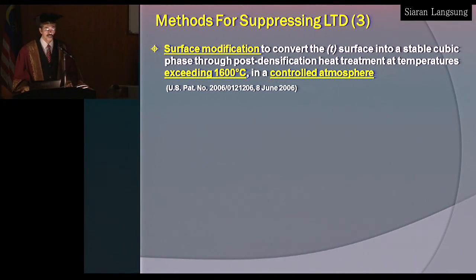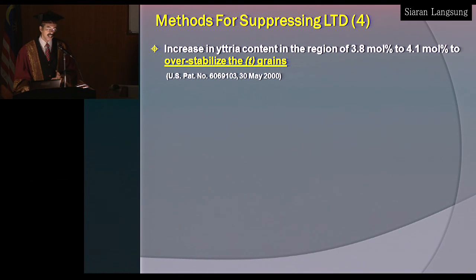The third method obviously is surface modification. This is done by converting just a micron layer of the tetragonal structure on the surface into the stable cubic form. This is done by using some post-heat treatment processes at very high temperature and in controlled atmosphere. Now the cubic structure is known to be stable because it has high yttria content, so it will not react to hydroxyl. In the tetragonal form, the stabilizer content is insufficient to create that boundary to prevent hydroxyl from reacting. But the downside of having a cubic structure is that transformation toughening is affected, because for that to be fully effective, it needs to be in the fully tetragonal form.